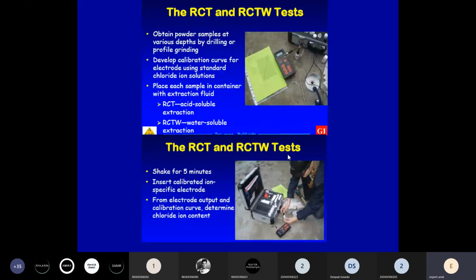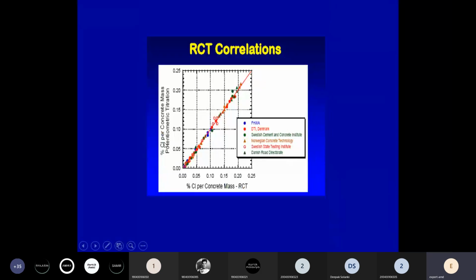Now coming to how to determine the chloride content at site. We have equipment called the rapid chloride test kit. We extract the concrete powder at site, and then we use the calibrated solutions provided by the manufacturers, and by using their curve, which is the curve between potentiometric titration and chloride per concrete mass, we try to find out the chloride content in hardened concrete. If you see our code, it states that chloride content in hardened concrete should not be more than 0.6 kg per meter cube if it's RCC. So when a reinforced concrete construction is the case, it should be lower than 0.6 kg per meter cube. If it is more than that, it simply indicates that the water which was used for construction was containing a high amount of chloride,